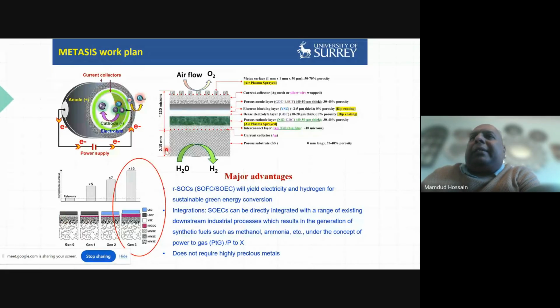Now our structure has stainless steel as a support material, and we can now have an electrolyte which is very thin. We can have an anode and cathode which are very thin, because all is supported on our substrate, a porous tube made of stainless steel. So we can reduce the electrical resistance that I talked about in answering one of the questions. We can make it thinner to reduce electrical resistance.